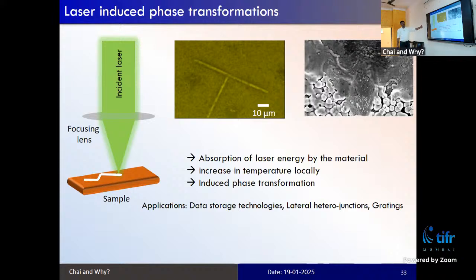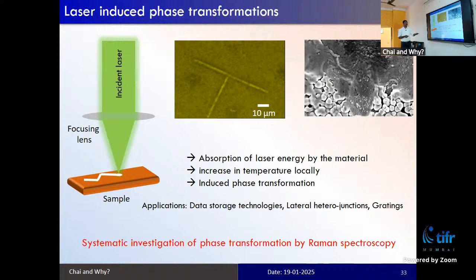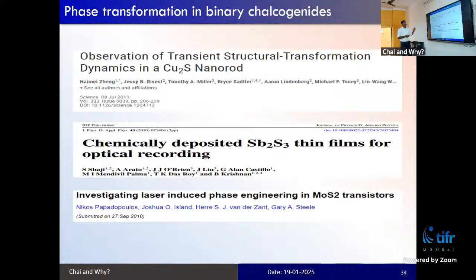We used a green laser with 30 milliwatt of power, and it damages the surface. This is the SEM image of the copper antimony sulfide, and even in the optical image, you can see that the surface morphology is changing. So we wanted to investigate deeply what we can do with this type of phase transformation. We systematically investigated this phase transformation using Raman spectroscopy. This type of phase transformation has been previously reported in other materials like copper sulfide and antimony sulfide, but until now it has not been reported for copper antimony sulfide.